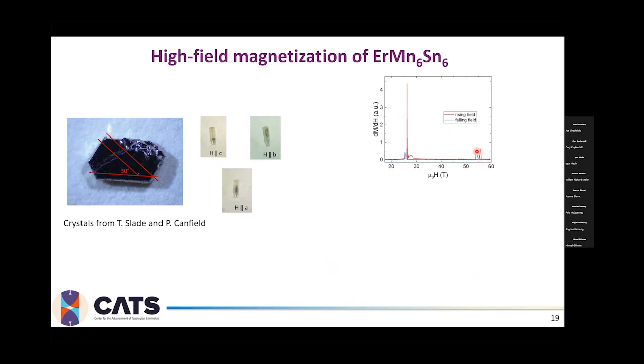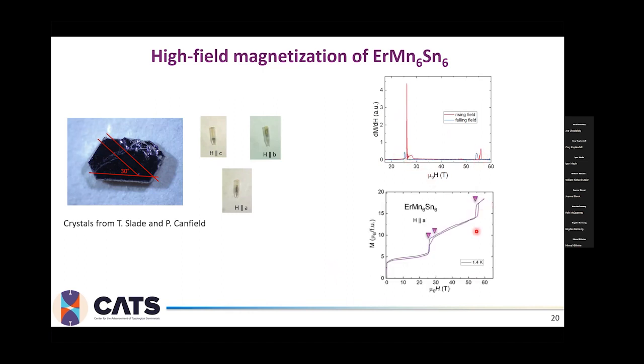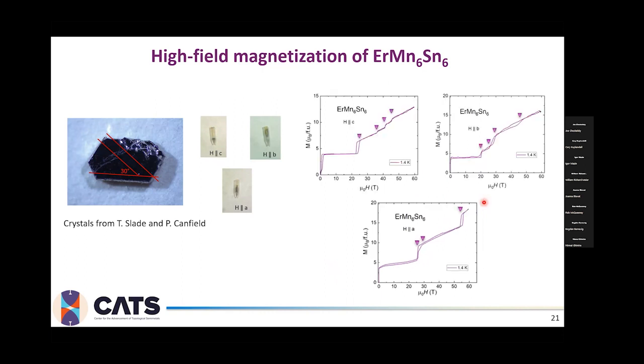So this also suggests to me that there may be some hysteresis. When we look at the magnetization, there is a transition around 25 Tesla, which is represented by this double peak over here. And there's also one more transition around 55 Tesla. So when we take a closer look, how does it change along the A, B, and C direction?